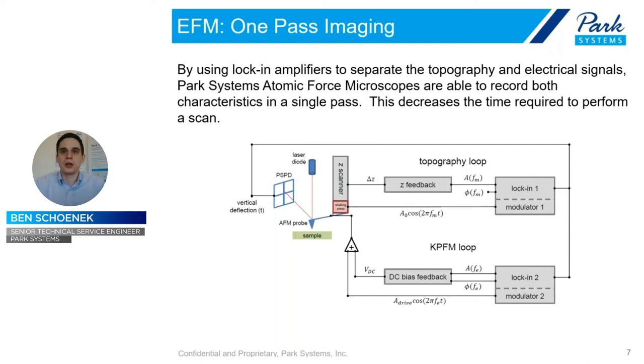We're going to focus in detail on a very specific component of sideband KPFM, which means focusing on the lock-in amplifier loop. To do one-pass imaging — taking the electric information and topography at the same time — we use a piece of equipment known as a lock-in amplifier. It allows us to measure not only the topography but also the electric information by separating the two signals from each other as we pass over. This solves the issue of imaging taking twice as long, because we can gather both sets of information at the same time.